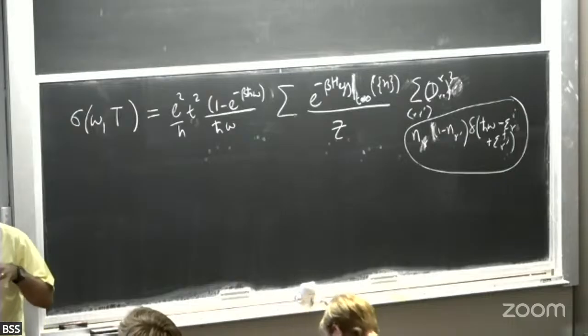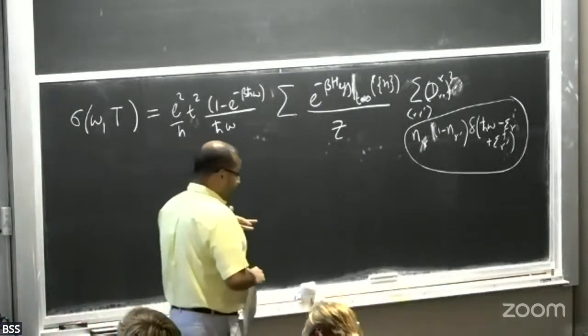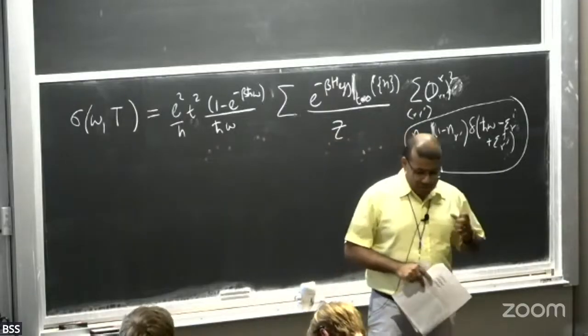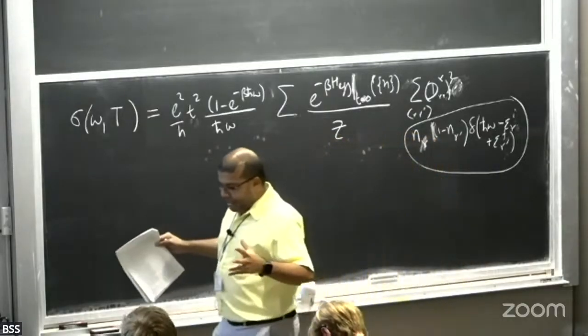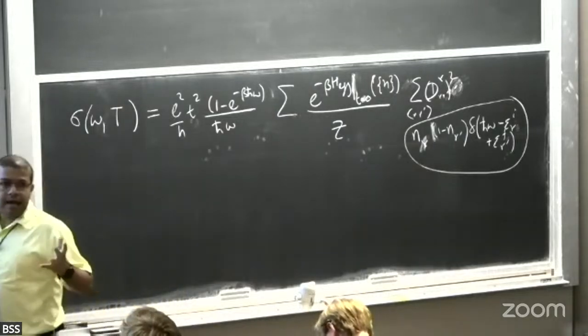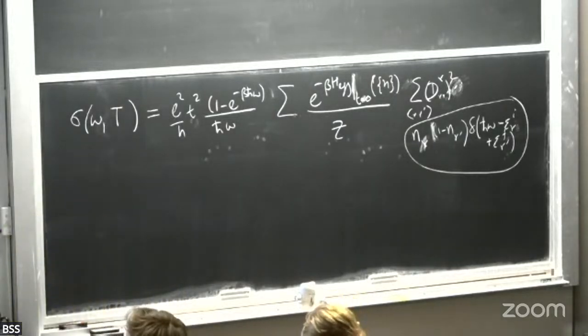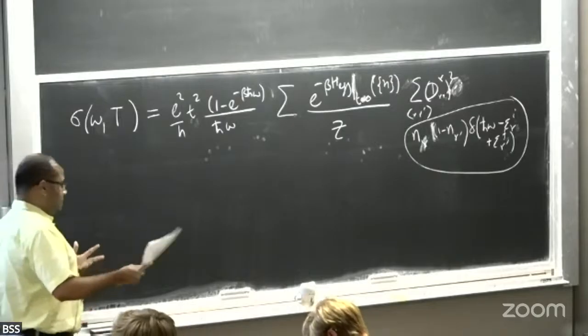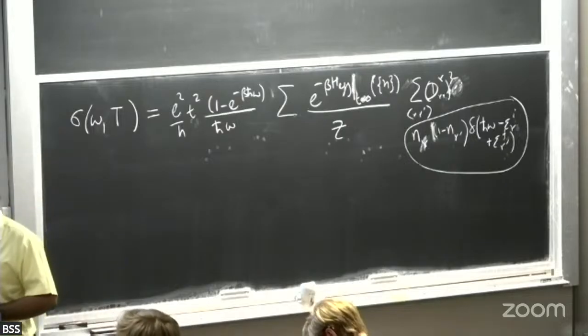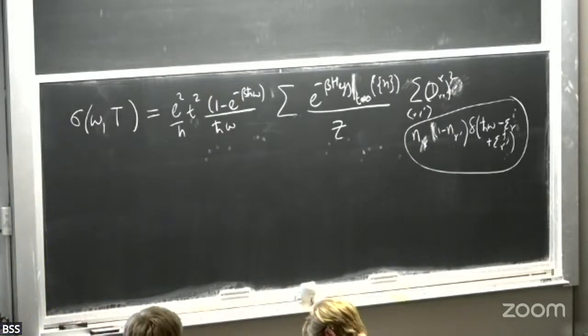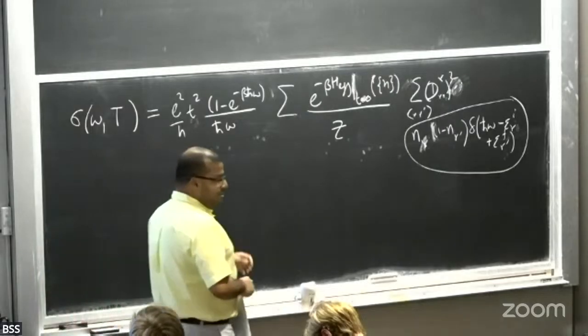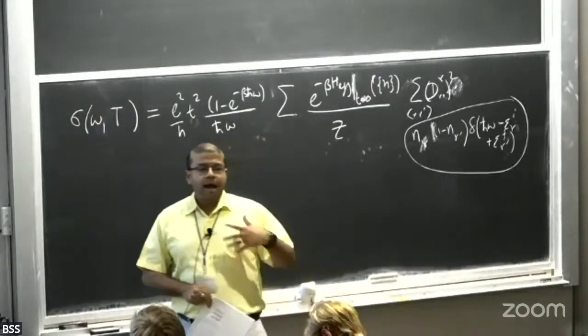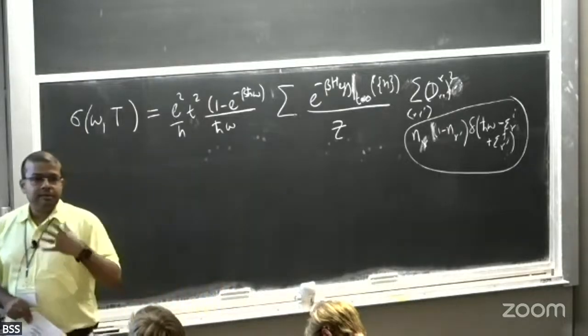And the best part of studying this material is that one of the biggest challenges with transport is that you can't disentangle the electron-electron scattering from electron-phonon scattering. I just give you the resistivity. How do you know whether it's coming from some conspiracy of the electron-electron, electron-phonon, and so on? And for instance, even in the cuprates, imagine if you had a purely electronic theory for what gives you T-linear resistivity. I can always ask, okay, so now what happens if I start adding phonons? How will they affect the scattering rate?